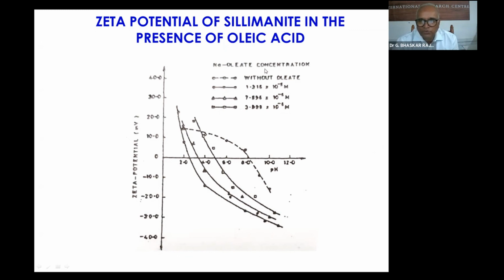So I have used the oleate, and when it is adsorbed on this sillimanite, your zeta potential, the point of zero charge or IEP values, will get shifted with the concentration. You can observe the shift in the pH after the adsorption of these things.